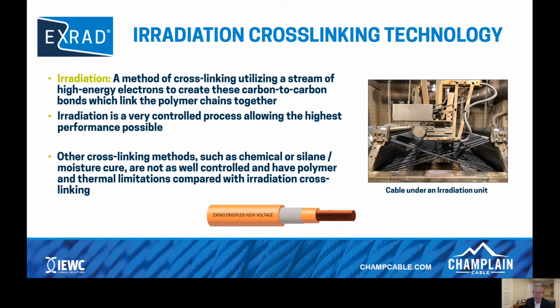And this is a real important point. With irradiation, we control the amount of irradiation. We control the dosage for each particular material that we have. And that's kind of a big deal because not every material wants the exact same dosage of cross-linking. You can think about it on a spectrum. A little higher cross-linking may not optimize that material, and too low a degree of cross-linking will not optimize that material. But you find the perfect amount of cross-linking for that material to optimize the performance of that material and make it the best that it can be.